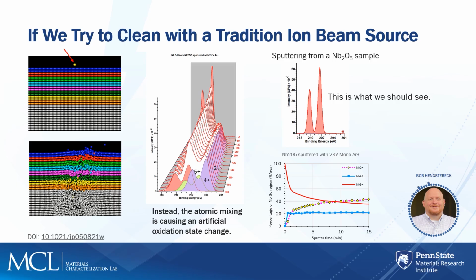What does that mean in terms of our materials? Well, this is a good example. This is real data taken from Nb2O5 single crystal material, where we've sputtered it with a 2 kV argon species. And essentially, with that first sputtering event, we see a reduction from +5 to +4 towards +3. And so we can show, as documented in the lower slide, that as we sputter continuously, we lose the +5, we start developing more +3, and we even have some +4. Eventually, it'll go all to +3. But essentially what's happened is we're preferentially sputtering oxygen and changing the chemistry.